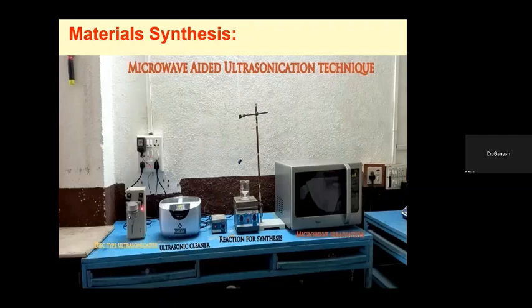It has a power of 800 watts, and this is the rod with a disc situated at the tip, and its frequency is 40 kilohertz. This is the ultrasonic cleaner, which cleans at a frequency of 24 kilohertz. This is the assembly of the actual reaction on the magnetic stirrer with hot plate, and this is the microwave oven. So here the microwave aided ultrasonication technique is used to fabricate the nanomaterials.